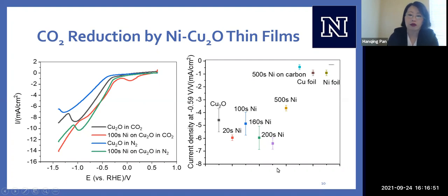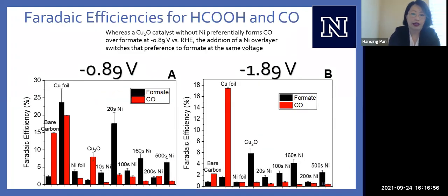So linear sweep voltammetry can only tell us so much. We really need to quantify our products. So let's do that. We did this reaction under two different voltages. One is at a little less mild of a voltage and one at a much more harsh, much more negative voltage. Two interesting things can happen when you push a reaction that hard. One is that it could completely shut down your reaction and we see no other products but hydrogen. Or if you push your reaction hard enough, we can start to see some interesting products like methane and ethylene.